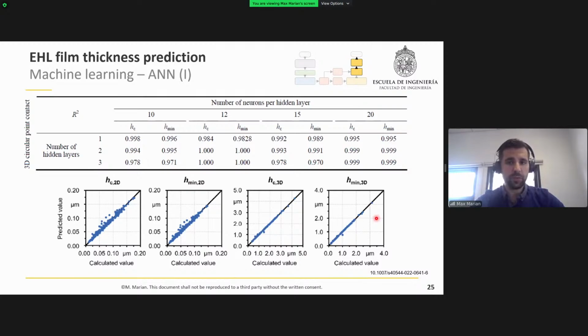On this slide, we can see some results for the neural networks, namely the coefficient of determination for the prediction of, again, the central and the minimum film thickness for the 2D line contact, and also for the 3D point contact. Again, the R square values are against testing data, and here we write the number of neurons per hidden layer, between 10 and 20, as well as the number of hidden layers, between 1 and 3.